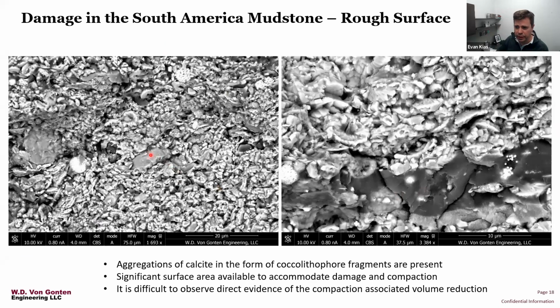If we take a closer look at those, one possible mechanism for the compaction of this sample could be lying within all of the void space and porosity that occurs within and around these coccolithophores. This is, of course, masked by the damaged state of these little critters themselves.